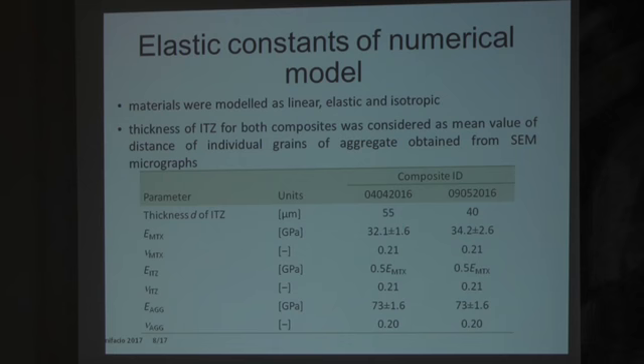The modulus of elasticity of the aggregate was taken from the literature, and also the Poisson ratios for the materials were taken from the literature. We also did some parametric study. We considered the change of the matrix modulus of elasticity. We take the mean value and the 5% and 95% quantiles.